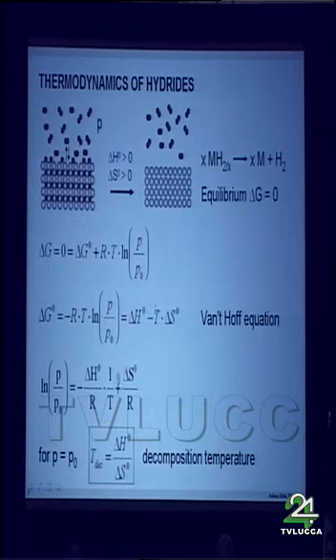And based on that, we find the Van 't Hoff equation, and with the Van 't Hoff equation at a pressure equal to P0, we can describe the decomposition temperature. So this will be very important for the discussion of other types of hydrides I will talk about later on, because often in not perfectly reversible systems, the decomposition temperature is the important parameter. But once again, the decomposition temperature is only a real measurement if we are in equilibrium and if the pressure is equal to P0, which means if the pressure is 1 bar or 10 to the 5 Pascal.